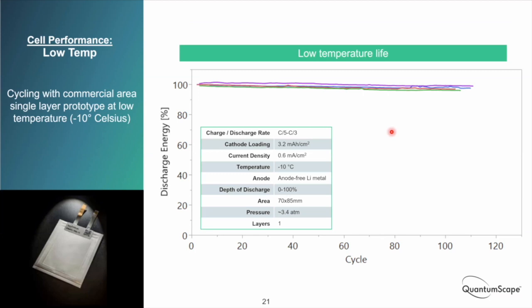So then we wanted to show cycling at low temperatures. This would be representative of real world winter driving conditions. Minus 10 degrees C, charging at C/5 and discharging at C/3 repeatedly. This is showing performance of our cells across winter, showing that they retain a lot of capacity. And again, these were the same generation of cell, this single layer pouch cell, same cathode thickness, everything else. So I think solid state cells can work well at low temperature. This is some encouraging evidence.